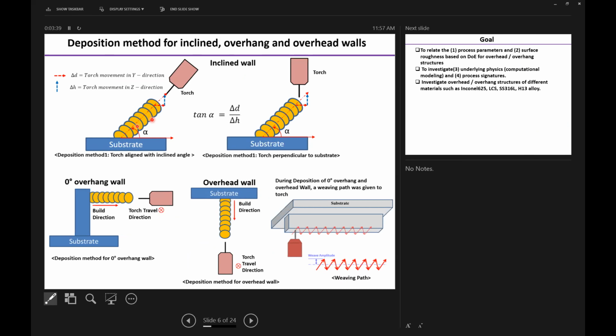So here, this first figure shows the deposition method for depositing the incline wall when the torch is aligned with the incline angle. For depositing an incline wall, after depositing one layer, you have to move the torch in the horizontal as well as in the vertical direction. That will give you the inclination angle alpha, based upon this formula: tan alpha is equal to delta D by delta H. So delta D is the movement of the torch in the Y direction, and delta H is the movement of the torch in the Z direction.